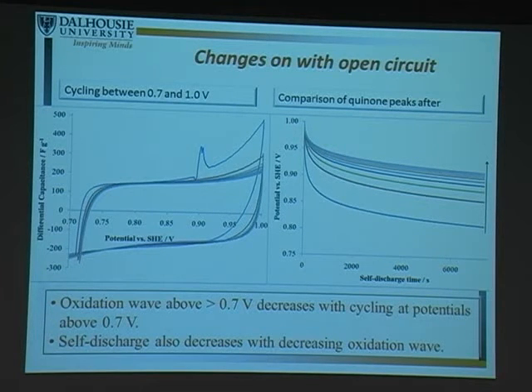We also wanted to decide, does the self-discharge relate only to this oxidation wave? Does it need to have any quinone? And we see that here. Again, we're looking at the CV, but only from above 0.7 up to 1. The other key here is with the other CVs, we were going down to 0 volts. One of the things we're always concerned about is we know that there's oxygen reduction in the cell.